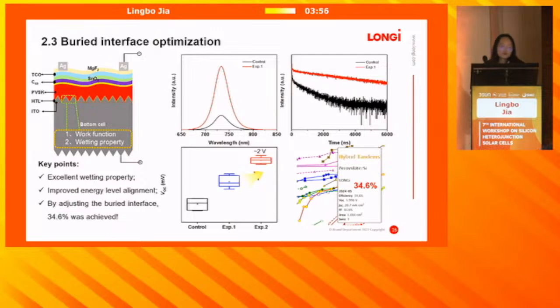We know that the work function of HTL materials and also the wetting property can help us to form the good crystallinity of perovskite films and also facilitate the charge transfer. So here we designed and synthesized a novel HTL material to replace the commonly used materials like 2PACz, 4PACz. And here, by using our materials, we achieved excellent wetting properties and also improved the energy level alignments between perovskite films and the TCO. So by using these materials, we can finally achieve an enhanced voltage to nearly 2 volts.